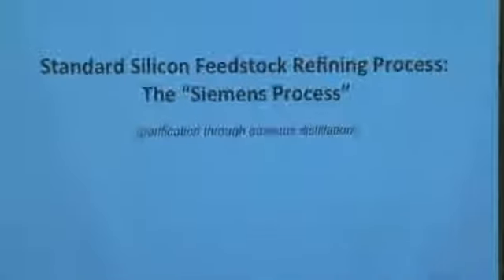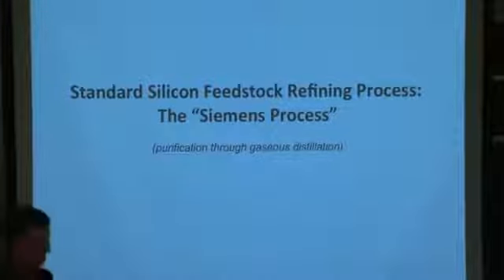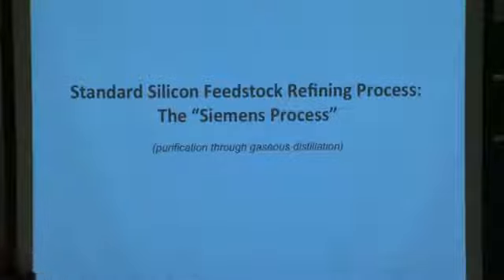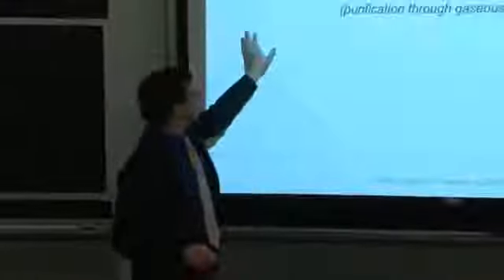So let me talk about going from metallurgical grade silicon, about 2 nines to 3 nines pure. When I say 2 nines, it means 99%. 3 nines would be 99.9% pure, to silicon that we can use for solar cells, which typically has to be about 6 nines pure. This is called the Siemens process, which is purification through gaseous distillation. And that's the method that is currently used to make most of our silicon.